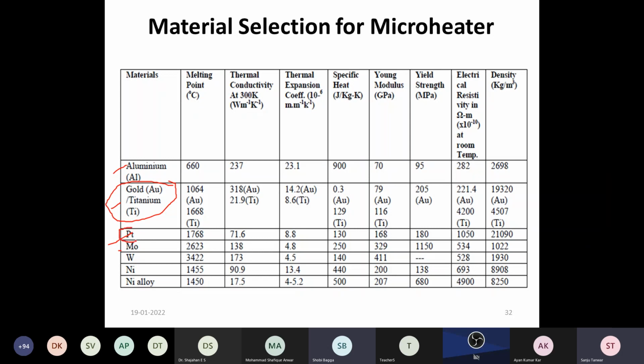People use platinum extensively. Platinum gives you the advantage that it is a noble material and is not affected by an oxidizing atmosphere. People use it extensively, but the main problem with platinum is the cost. When we want to develop a low-cost gas sensor, we can't go for platinum. Molybdenum and tungsten also have high melting points, so people avoid them. Therefore, in the present work, we have used nichrome, which is basically a nickel alloy. Nickel plus chromium is the nichrome alloy. We have used nichrome to develop the coplanar microheater platform because it has high resistivity and low cost.